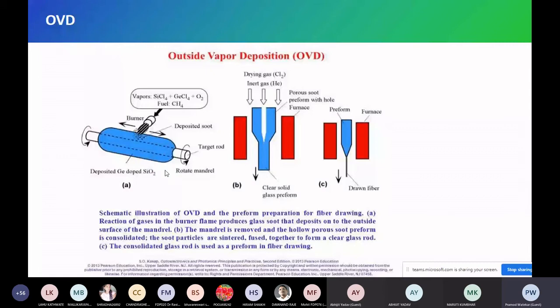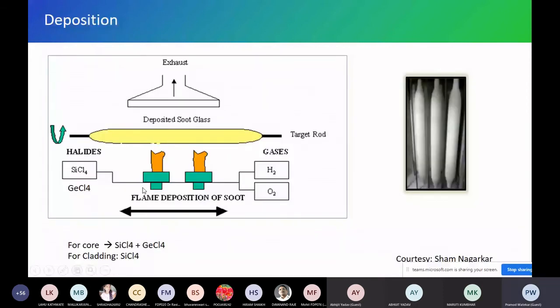We use this OVD glass. So I will show you here how it is done. I think this is visible to you. On the right side we can see there are white colored rods. These are called soot rods. How does this soot look? It is not glass. It is soot, white color, ash type. Because temperature is low, SiO2 is in particle form. Micron particles, 5 micron, 4 micron, that type. So we have micron particles. They become soot like these things. So we take this soot, then put it in the furnace. It becomes glass.